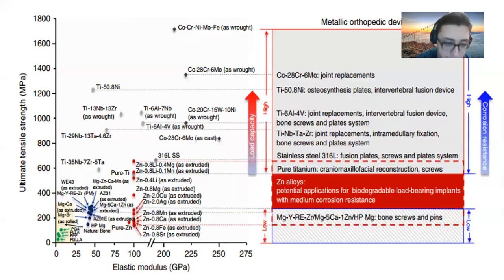So here's a table. We're going to go through this table in a bit of detail. As you can see, magnesium alloys are in here between 200 and 400 megapascals. They are really only used in bone screws and pins. And then up there is titanium. You know, titanium is quite good. And in between, there's a gap, right? We can fill that gap with zinc alloys that are biodegradable. The biodegradability, especially, is very important in medical performance because it removes the necessity of a secondary surgery to remove the implant. And it also removes the concept known as stress shielding, which is when implants take over the load, so bone density gets lower because the bone doesn't carry any load.